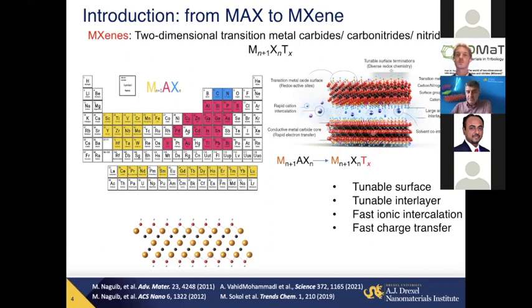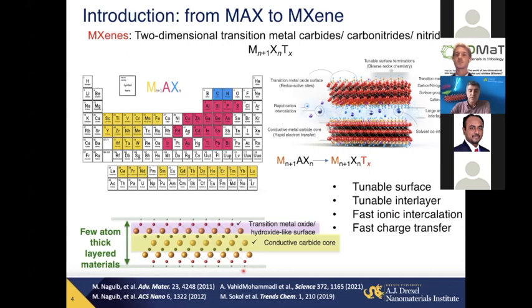And these sheets produced have tunable surfaces, tunable interlayers, fast ionic intercalation, fast charge transfer, and many other interesting characteristics. What is also interesting is that the majority of them are metallic, conducting, but their surface looks like the surface of a transition metal oxide or hydroxide, so they can be easily dispersed in water. And they are, of course, just a couple of atoms thin, so those are in fact two-dimensional materials.